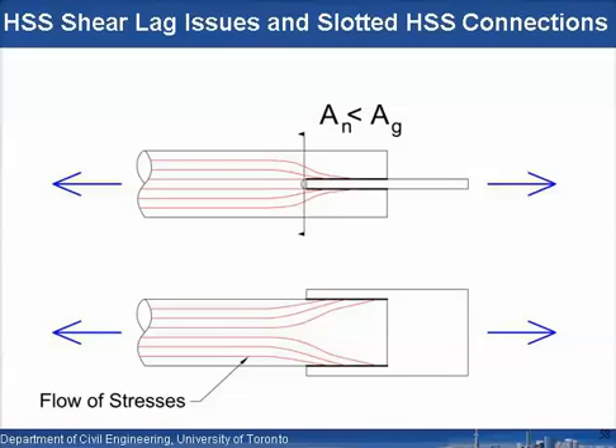And then, due to this phenomenon called shear lag, because you're only applying the load into this brace member on two sides, it's being applied on one point of the circumference by the plate, and then at 180 degrees around the tube at the other point, we have the tube non-equally loaded. It's highly loaded on two parts of the perimeter and unloaded on some other parts of the perimeter. So therefore, the shear strains in part of the cross-section lag the shear strains in other parts of the cross-section, so we have a phenomenon called shear lag. This then tends to reduce the capacity of the cross-section as well, and makes it prone to fracture across this critical cross-section here, which is shown on that diagram.